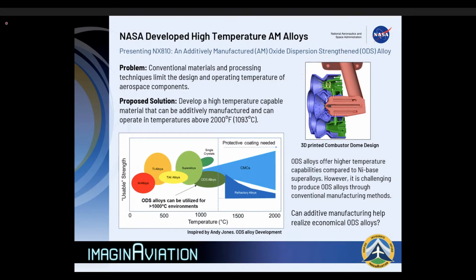And you can imagine, oxides being much less dense than your metal. If you melt the metal, all of those oxides will just float to the top. And so being able to cast a part with these little oxides in your component is just impossible. And so they developed this really complex processing route where you basically mechanically alloy the oxides by just slamming it into the metal powder over and over, and then consolidating that powder into a part. And because of how complex that process is, ODS alloys really never became economical, and other than some special cases, just weren't used within industry. And so a lot of the research and development of ODS alloys fell away.